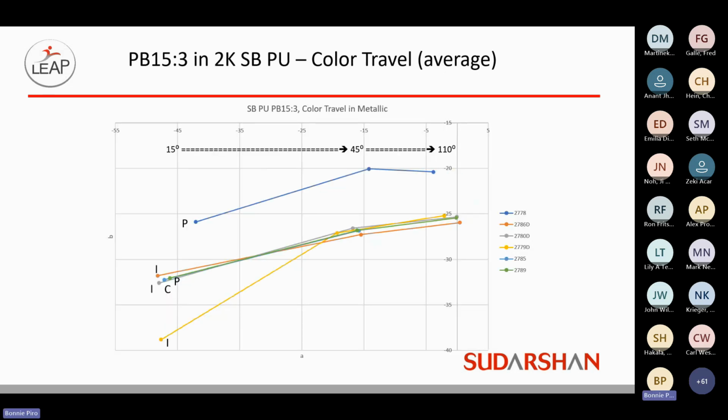Color travel, like we saw with all the indexes here. Here we get to see how the finishing impacts the color travel of the Pigment Blue 15:3. If you recall, we mentioned that the betas have the most red to green travel and the least blue to yellow travel. When we take a look at just the products in that 15:3 category, we see a variety of differences. The bulk of them look about the same. However, we do have one ink product that does travel more than the others, and one of the plastics-created materials has less travel. So again, some options to consider when developing a formulation.